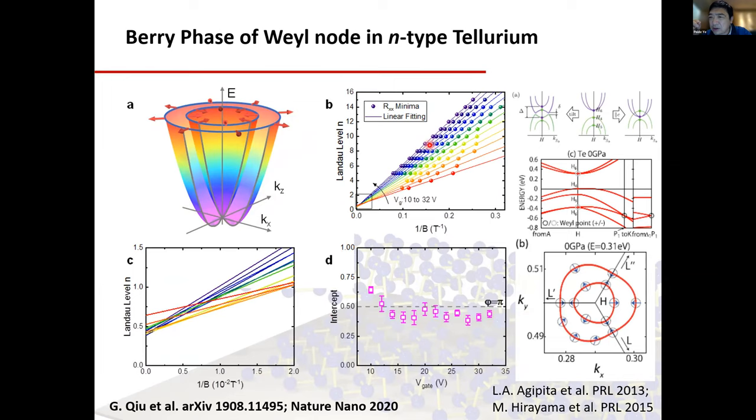The transport quality is already good enough to determine the minimum and maximum, and fit to the Landau fan. That's already good enough. In this case, you can clearly see the offset. Of course, you need to use the minimum. Some papers probably even confuse the minimum and maximum, that's another issue. So you fit to this curve, and you can see the offset is 0.5 instead of 0, like gallium arsenide,